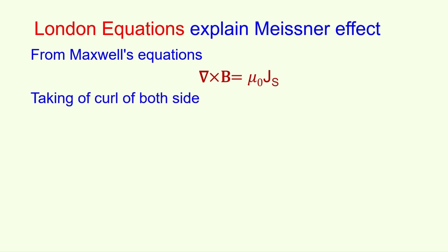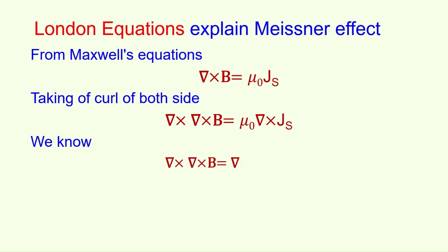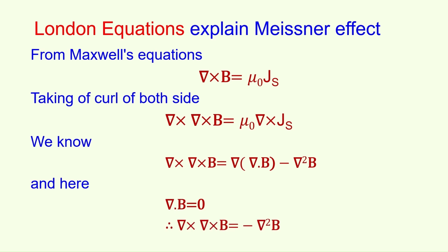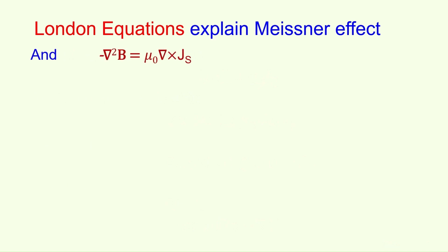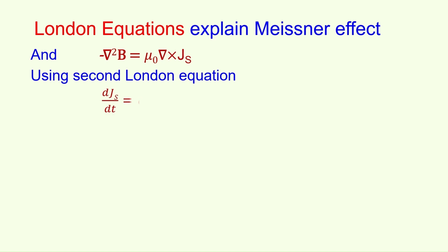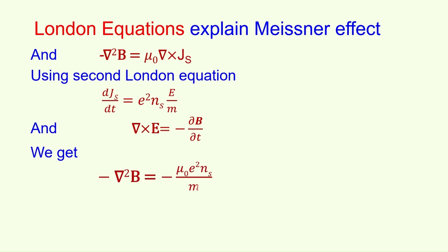From Maxwell's equations, del cross B equals mu 0 Js. Taking the curl of both sides, del cross del cross B equals mu 0 del cross Js. We know del cross del cross B equals del of del dot B minus del squared B. And here, del dot B equals 0. Therefore del cross del cross B equals minus del squared B, and minus del squared B equals mu 0 del cross Js. Using the second London equation, del cross Js equals e squared ns divided by m times B, we get del squared B equals mu 0 e squared ns divided by m times B, or del squared B equals 1 divided by lambda squared times B.